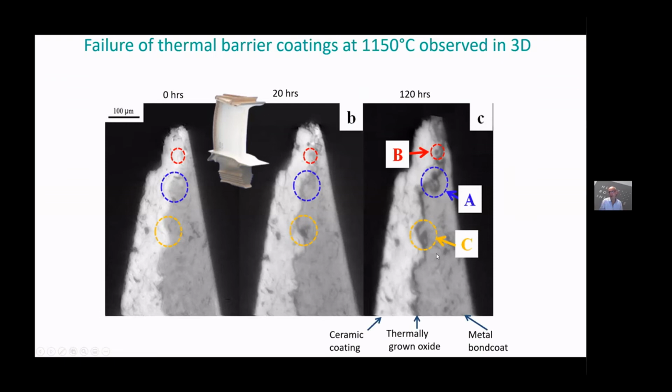And so we can start to understand, just as some parts of that diagram that Michael was showing in the last talk, where we were talking about different conditions for failures. Well, here we can understand why coating defects occur at the interface between the coating and the substrate, and these defects can lead ultimately to spalling of the coating.